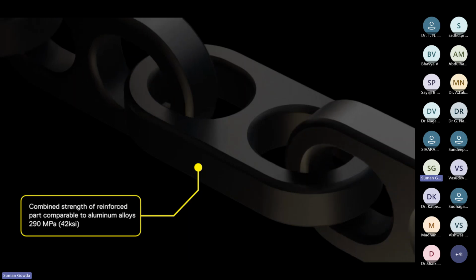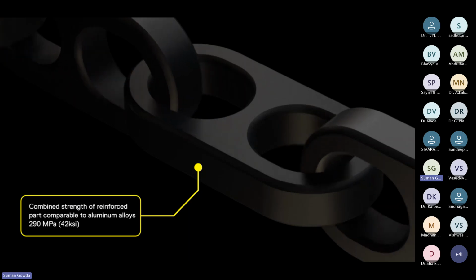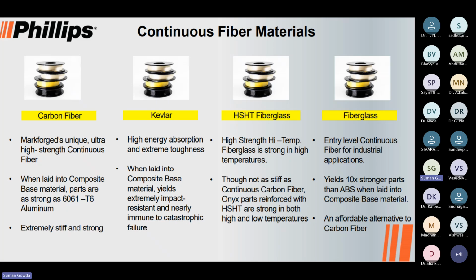Now it depends upon the orientation. I'm going to get a certain amount of fiber when the part is at a laid down position, but when the same part is in a standing orientation, the amount of fiber that is being deposited will be completely different. So you can go into the Eiger.io link and then upload the model, or just start working on the model. Then you can start to realize the kind of difference that you will be getting. So once again, these are the 4 fibers that are being used.